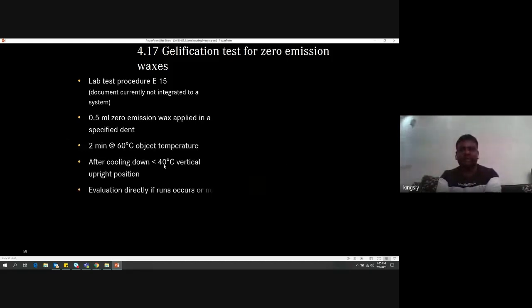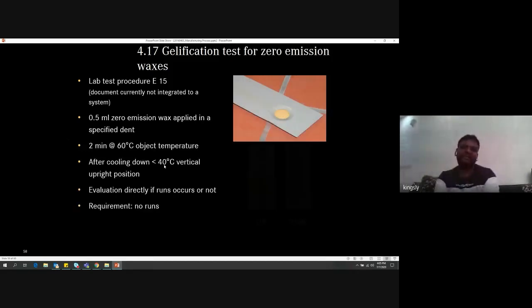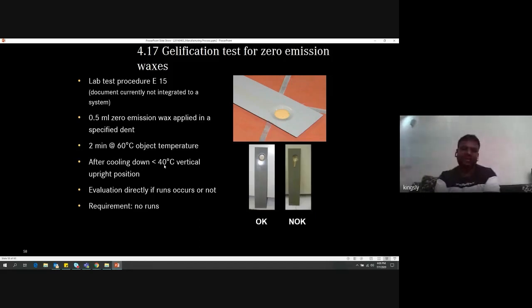Then we also do the zero emission test for the wax area, because wax material is flammable. Since we apply this for corrosion protection, after applying it we also check the property. It should not catch flame. Based on that, this wax material will be added with binders, so that when we spray this wax, it does not flow around. So this should not be in the exposure area.